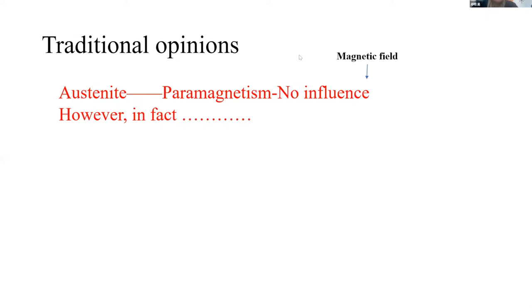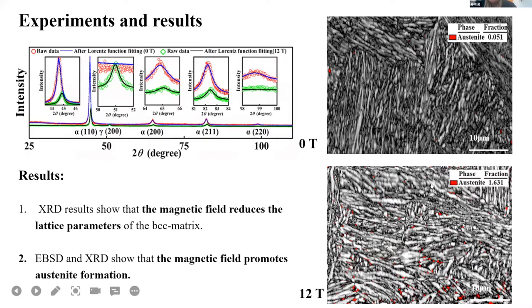The other very interesting phenomenon is about the austenite. The austenite in our experiment should be paramagnetic, so the external field should have no influence on it. But in fact, the red points or red areas represent that the fraction of austenite increased compared with the austenite fraction without the magnetic field. It means that in our experiment, the retained austenite volume fraction increases. Why does that happen? It makes no sense.